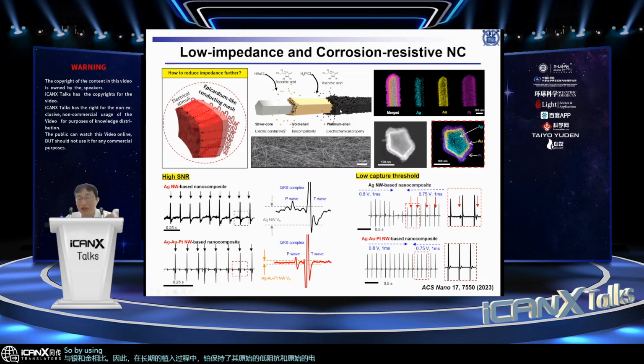So by simply changing the material from gold-shell nanowire to platinum-shell nanowire, the contact impedance could be decreased. Therefore, the signal-to-noise ratio and sensing could be increased, and electrical stimulation efficacy could be improved.